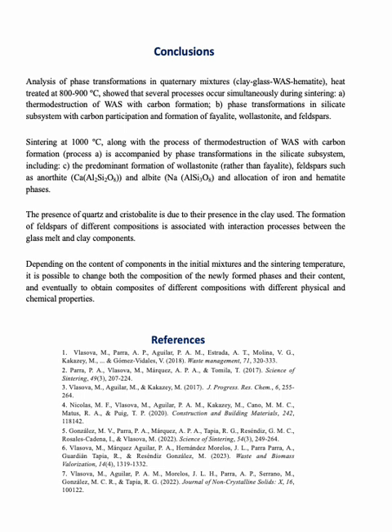The sintering of samples at 1000 degrees Celsius presents a thermodestruction of waste with carbon formation and is accompanied by phase transformation in the silicate subsystem, including the predominant formation of wollastonite, feldspars, anorthite and albite, and allocation of iron and hematite phases. The presence of quartz and cristobalite is due to their presence in the clay used. The formation of feldspars of different composition is associated with the interaction process between the glass and clay components. Depending on the content of the components in the initial mixtures and the sinter temperature, it is possible to change both the composition of newly formed phases and their content, and eventually to obtain composites of different compositions with different physical and chemical properties. Thank you very much.